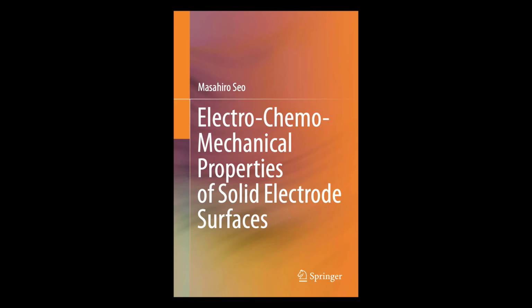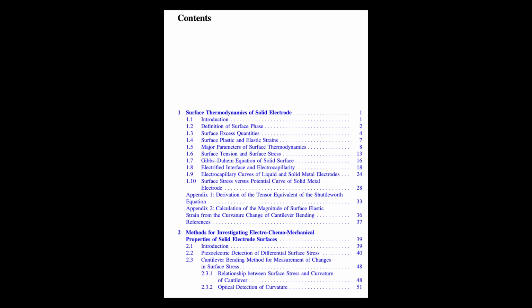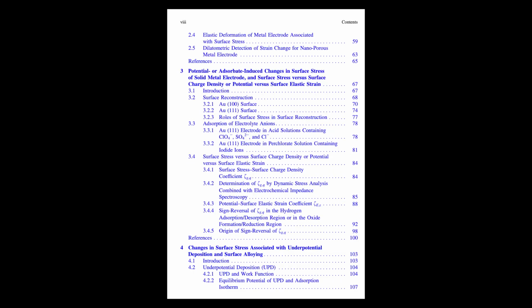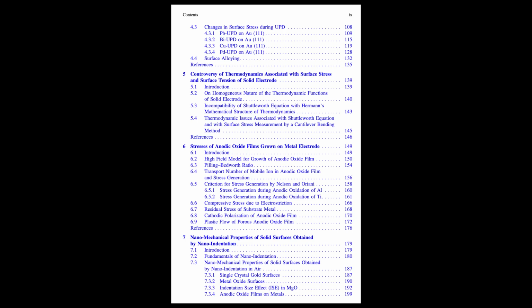You've got it. And the equilibrium potential for UPD, the point where a certain amount is stable on the surface, follows adsorption isotherms, much like gas adsorption. Yeah. You can even use models like the Langmuir isotherm to describe it. And I'm guessing adding this new layer of atoms is going to mess with the surface stress of the substrate, right? Oh, absolutely. A classic example is lead, Pb, UPD on gold (111). Lead atoms are quite a bit larger than gold atoms. Right. So initially, as lead atoms adsorb, they tend to induce compressive stress. They're sort of squeezing the gold surface. Makes sense. Bigger atoms trying to fit.